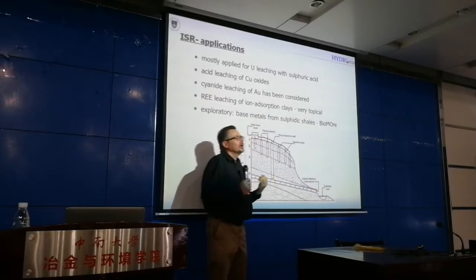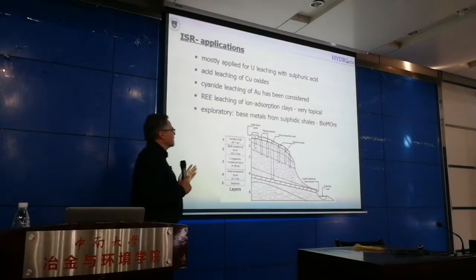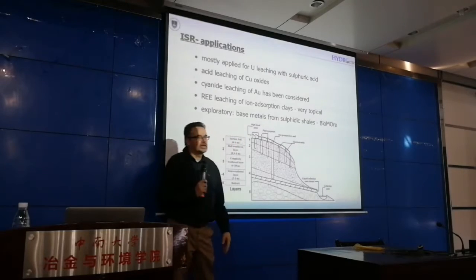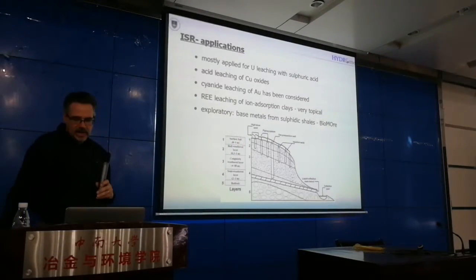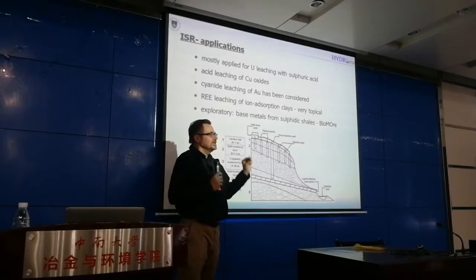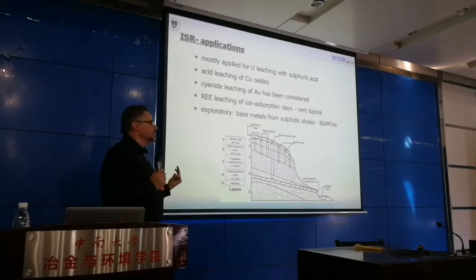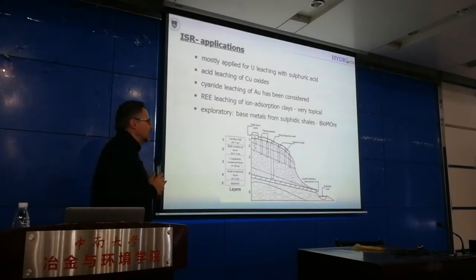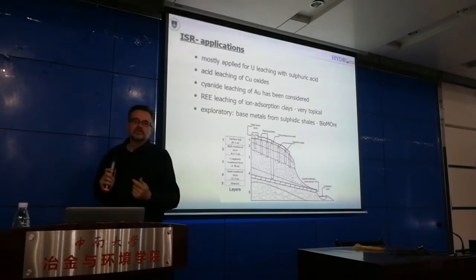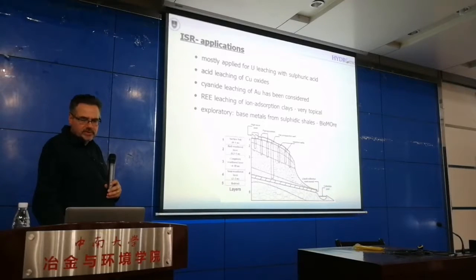So it's a little bit of a hybrid of heap leaching and in situ leaching, but sulfidic and to use it to basically have a shale material underground. Again, you fracture it through explosives, you inject a ferric iron solution, extract copper in particular, and then you pump it back underground, overground. And here you use biological reoxidation of ferrous to ferric, but again, that could equally well be done using an oxidant such as hydrogen peroxide.